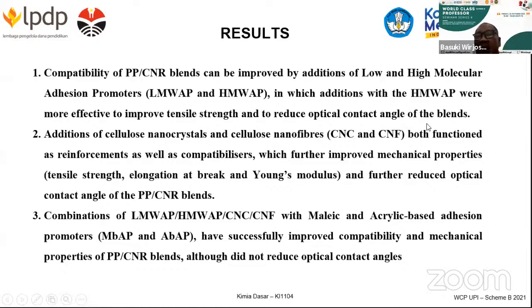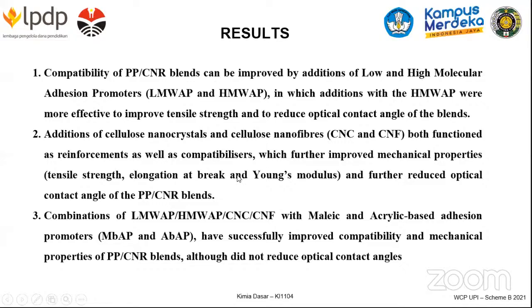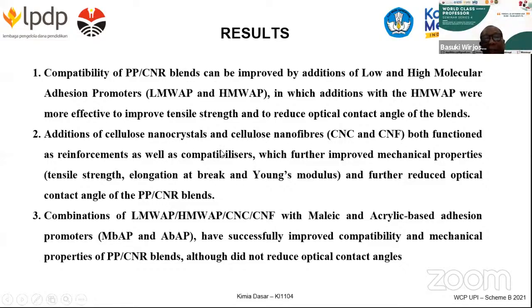What does it mean? We measure the surface hydrophilicity using the contact angle. A higher contact angle means the surface is more hydrophobic, and if the angle is very small, it is hydrophilic in nature. If we add these nanocrystals and cellulose nanofibers, they can function as a compatibilizer as well. They improve the mechanical properties, tensile strength, elongation at break, and Young's modulus, and further reduce the contact angle of the polypropylene and cyclic rubber blends. It means that if the contact angle becomes smaller, the compatibility is better.